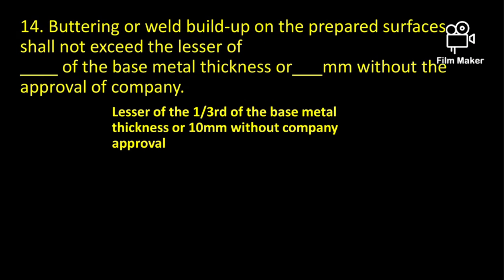Buttering or weld buildup on the prepared surfaces shall not exceed the lesser of one-third of base metal thickness or 10 mm without the approval of the company.